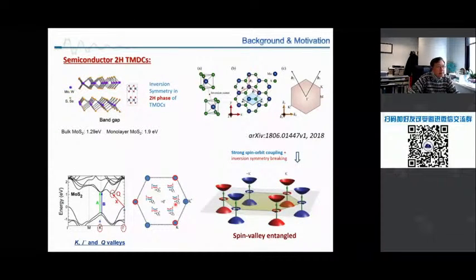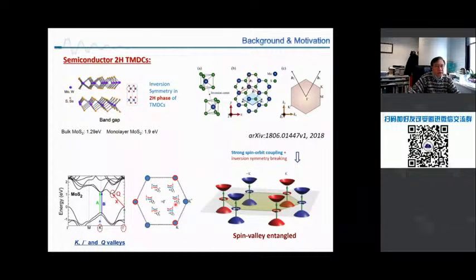So let's go into a little bit of detail about the band structure. This is the fundamentals for measuring those unconventional quantum phenomena. So this is 2H stacking, okay, and you see clearly inversion symmetry here. Once you exfoliate this material into a monolayer, it automatically breaks the so-called inversion symmetry.